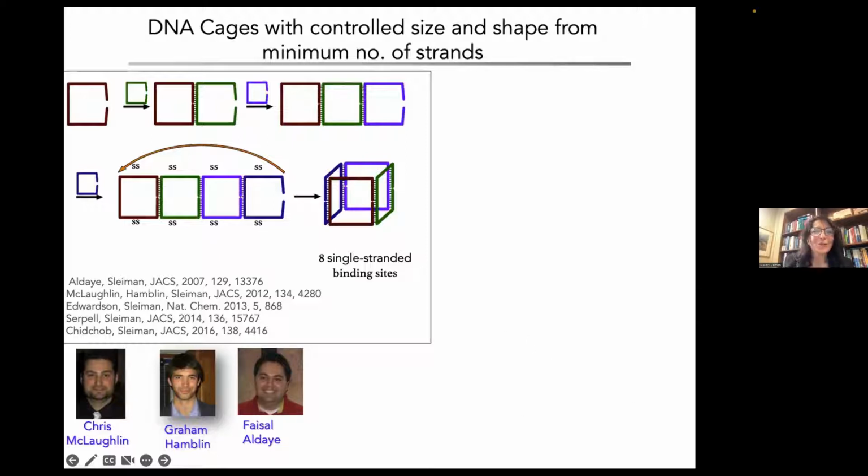So we start from our first strand shown right here. We can make DNA strands on a synthesizer, which we have in the lab, or we can design their sequence and order them from a supplier. We're going to design this part of the DNA strand and this part of the DNA strand to be complementary to the backside of this DNA strand shown right here, so that when these two come together and form a double helix, this and that close on this green strand. As you can see, this is now cyclized onto the green strand.